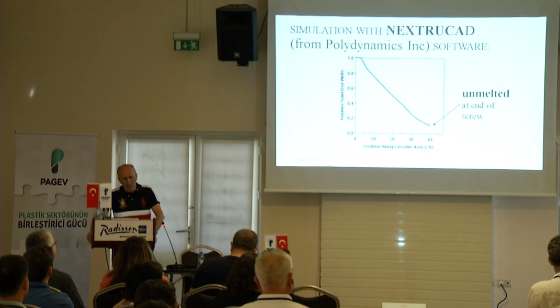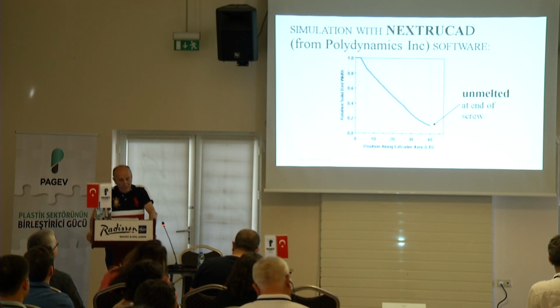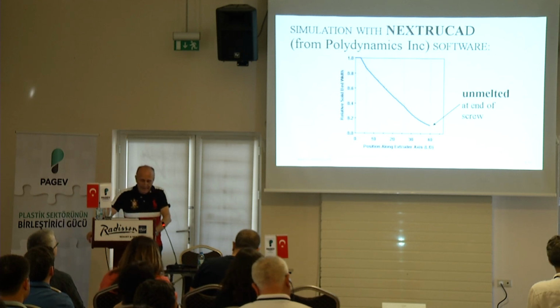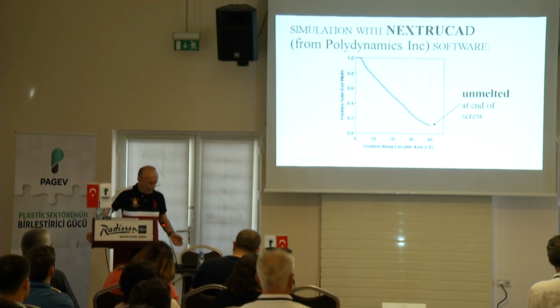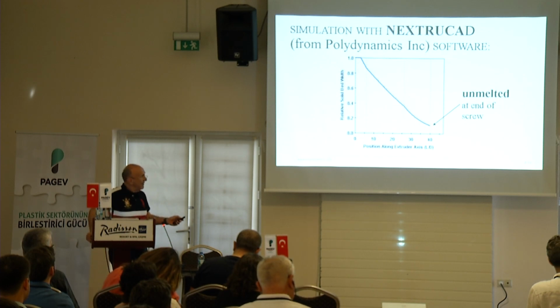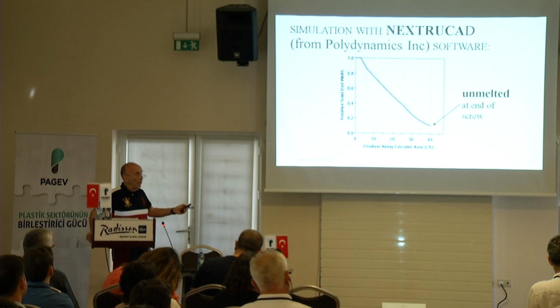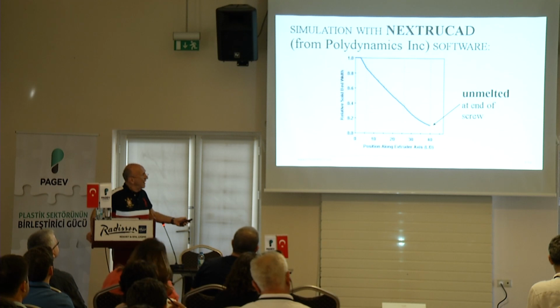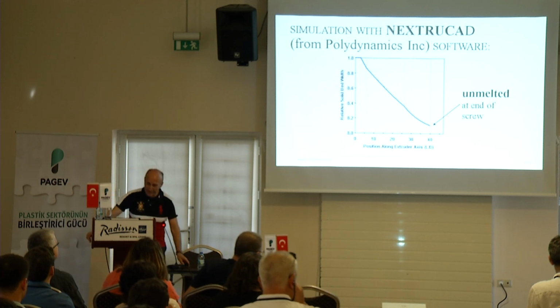And I did a computer simulation with my extrusion software package. It was a very long screw, L/D 40. And I discovered that, at the end of the screw, the software determines the melting. Under the hopper you have 100% solid, and then we determined the width of the solid bed, and at the end we had quite a bit, about 10% predicted unmelted material. But again,